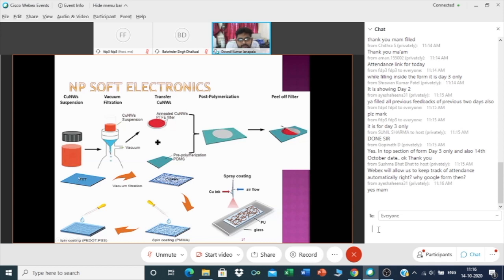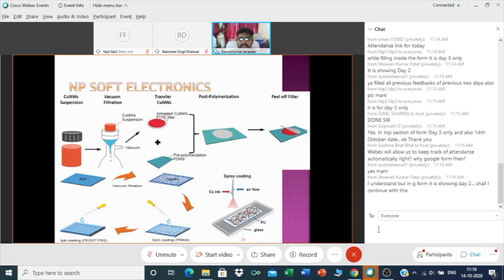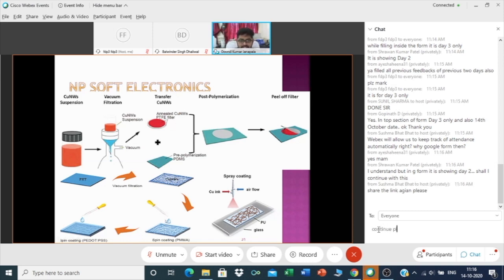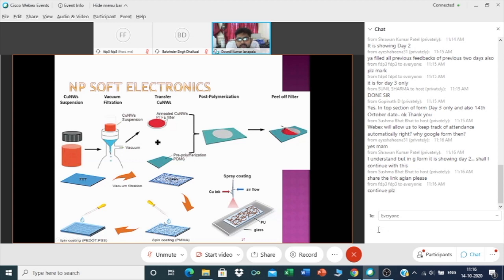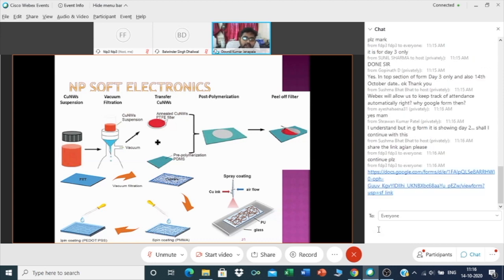Similarly, with a PET film, or whatever activated polymer you are taking, after that you will put your nanoparticles. You can put copper nanowires, copper nanoparticles, copper nanoflakes, whatever. You can use spray coating, laser sprinkling, ultrasonic spin coating, and several other things also. So once you coat that, this spin coating you can see here. This is one particular piece of equipment where in the middle you put your sample and put a drop of polymer, and you adjust your speed, and it will rotate and distribute your polymer equally. Why, I will tell you.